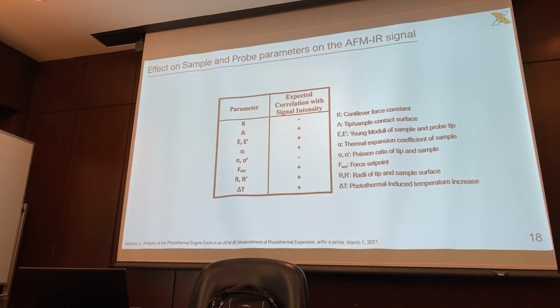Yes and no. I remember Kevin Green gave a talk during his prospectus, and he kind of explained some of this. In contact mode, you're going to see possibly the maximum amount of deformation of your material. It's more likely to cause sample deformation than tapping mode, where we're tapping at a constant frequency. You can still create some sample deformation if your sample is especially soft. I've experienced that myself with some of my softer samples, something like a soft polyisobutylene. So yes and no to answer your question.